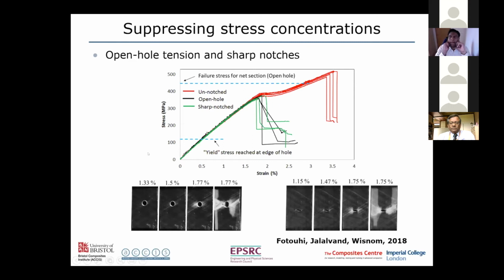And bearing in mind that actually around the edge of the hole here, it's reached this yield stress right down here. And all along here, as the load is increasing, we're seeing damage developing around the hole locally, redistributing the load and allowing us to go right up the way here before we get a final failure. You can't see it very clearly here, but there's already damage around the hole. Then as the strain increases, this propagates until at this point here, you've got full failure across the width of the section. So this is a very desirable characteristic to make the material less sensitive to notches and other stress concentrations.